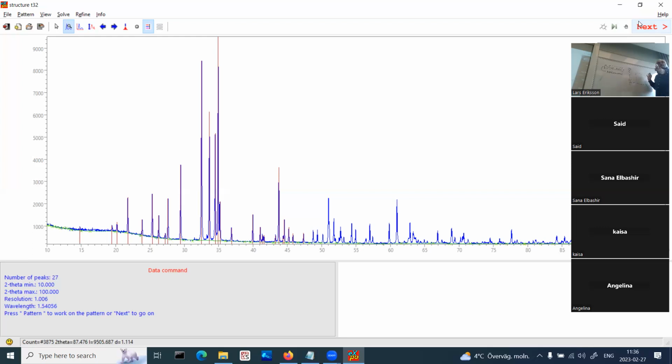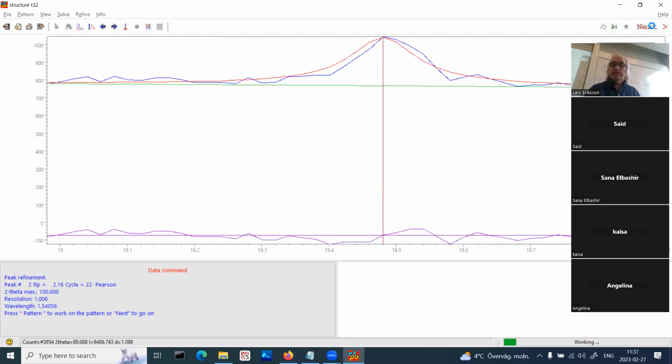You can try with all lines first. If you fail, then decrease the number of lines, say that you have 100 lines from the beginning, and you don't know the error function because you neglect to use the internal standard, because that is tricky. It takes half an hour extra. Then decrease the number of lines, and then the probability to succeed is much higher. Approximately as we did here. So clicking next.